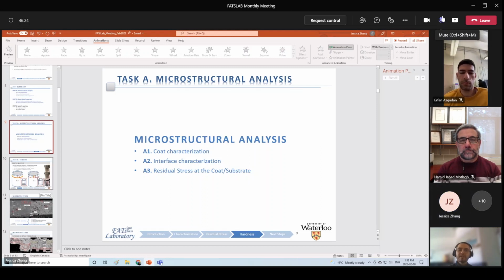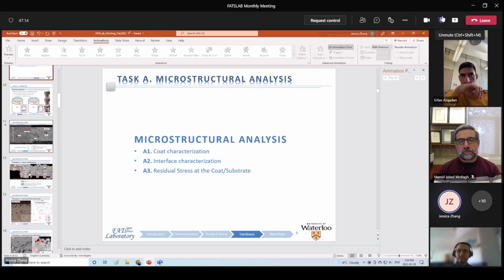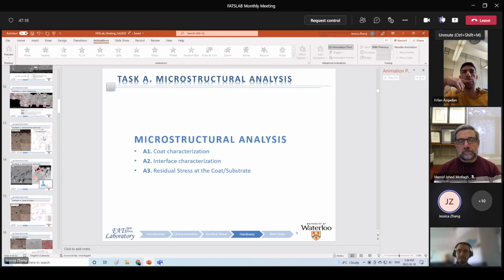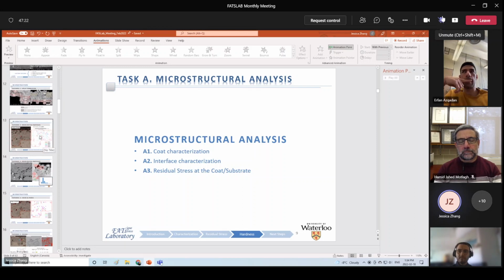Thanks, that answers my question. I guess from someone who's not familiar with coatings, like Erfan mentioned, maybe this is a foolish question, but do you think that the lack of intermetallic strength is specific to the coating you're dealing with, or does this apply more to this type of coating system in general? I think it more so applies to our particular samples because in thermal spray we have seen a variety of intermetallics present, which is why we were hoping to see something of the sort, because intermetallic bonding is very effective if we are able to achieve it compared to the mechanical. So I do think it pertains to these samples. Some people have suggested they have found it in similar samples, but we have yet to. But it is highly desired, in my opinion.